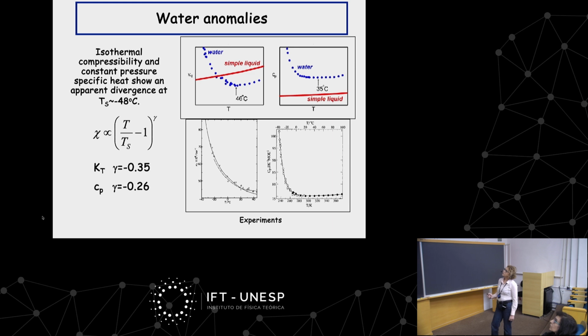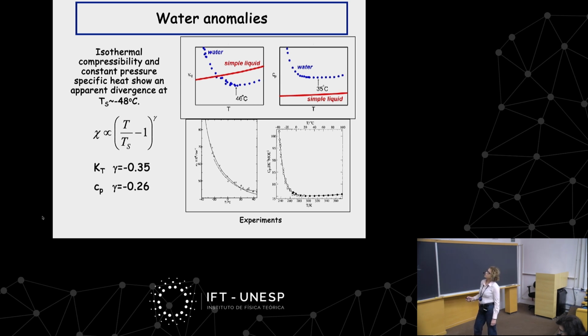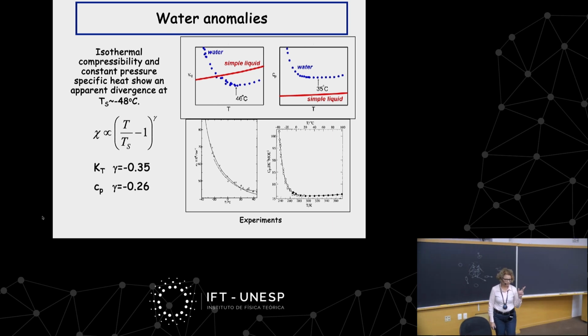Okay, water has many anomalies, and back when I started my research on water 30 years ago, people said there are apparent divergences of these quantities, isothermal compressibility and constant pressure specific heat. This in red that you see is the behavior of a simple liquid. This is the behavior of water. These are the experiments here, KT and CP. So there was this divergence, not so big because the exponent is not so high, but still an apparent divergence. We now know that this is not a divergence, but is the starting of a maximum.